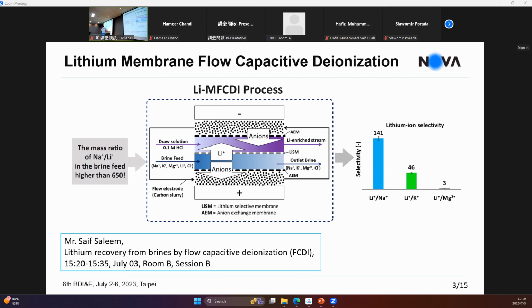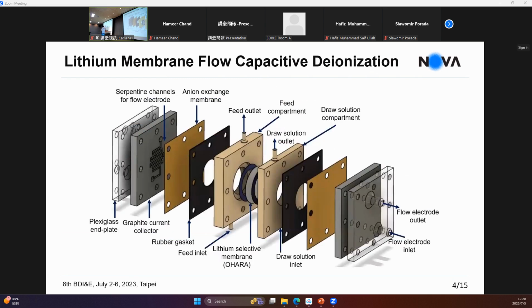And despite our feed brine being a sodium-rich brine, so with a much higher quantity of sodium than lithium, actually we were able to achieve some very interesting results and very good selectivity values and to recover the lithium successfully. I'm not going to explain this much more because our PhD student already presented this part of the work on Monday. But as in any FCDI-based process, one of the key elements of this technology are those current collectors and channels for the flow of flow electrodes.